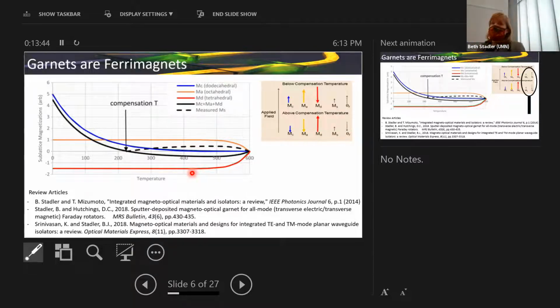There's this super exchange that happens with the oxygen between them. So if your tetrahedral sites are magnetized down, your octahedral sites will be magnetized up. That's how they align, unless you're close to the Curie temperature. But this dodecahedral site aligns with the octahedral magnetization, and you can see it actually gets pretty low here, then goes to 0.